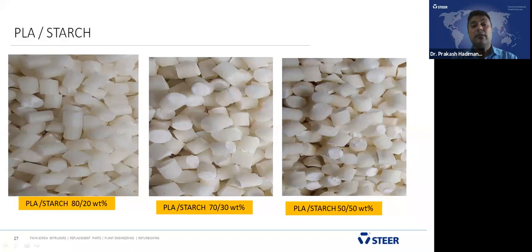It maintains surface smoothness and better color even at 30% starch. But only in the 50-50% starch, we observe a slight color change in the final compound, because the addition of starch increases the viscosity of the final compound. With this compound it's difficult to make blown film, and finally we could make injection molded particles and sheet lines.